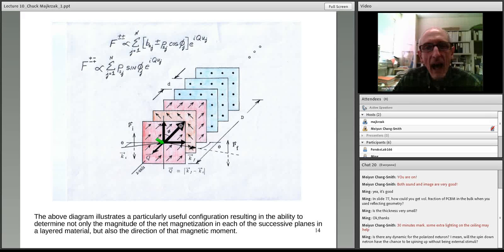in the non-spin flip mode, in other words, they come in as plus and go out as plus, or come in as minus and go out as minus, couple to the vertical component, the projection of the magnetization along this vertical axis. On the other hand, neutrons that come in and scatter via spin flip processes, so I prepare a beam that's plus and I measure a beam that's minus coming out, they couple to all components of the magnetization projected onto the horizontal plane.